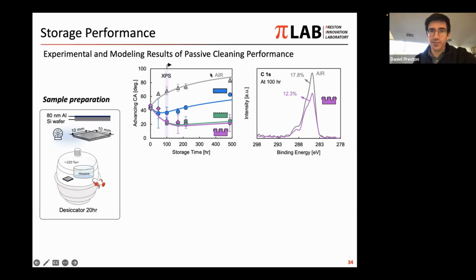In air, it continued to increase. What's interesting is that we see this sort of dip in the flat surface where we had some passive cleaning initially, but then we started to increase in contamination over time. And then the textured surfaces were quite effective at keeping the sample clean over time after initially having some passive cleaning performance.